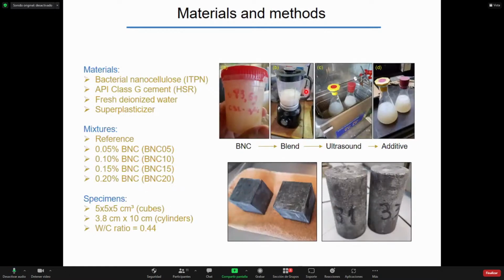Now we'll see the materials and methods used in this thesis. We use bacterial nanocellulose from the Institute of Technology on Polymers and Nanotechnology, and we blended it with fresh water, and we performed ultrasound in order to have a better distribution of bacterial nanocellulose in the mixture, in the final additive. We use API class G cement of high sulfate resistance, along with fresh water and superplasticizer. We use 5 types of mixtures, the first one with no bacterial nanocellulose in it, and the others up to 0.20% of bacterial nanocellulose by weight of cement. And we also use 2 types of specimens, cubes and cylinders, with a water to cement ratio of 0.44.